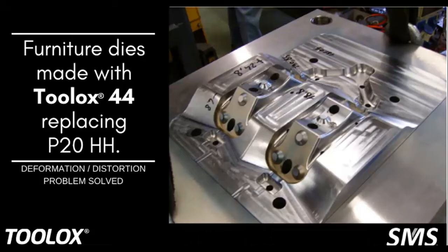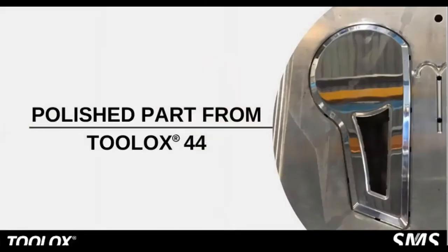The furniture dies have been made with Toolox 44, replacing P20HH. Deformation distortion problem solved. So this is a polished part made from Toolox 44, and there is a catch here: Toolox 44 polishability can go up to 5,000 mesh diamond polish. If you're looking for something like 8,000 or 10,000, which is usually derived only through stainless steel grades, it is not a stainless steel grade. So the maximum limit is 5,000 mesh. I think if you're using H13 or H13 or Orvar Supreme kind of material for your inserts, then we can pretty easily use Toolox 44 for similar applications.